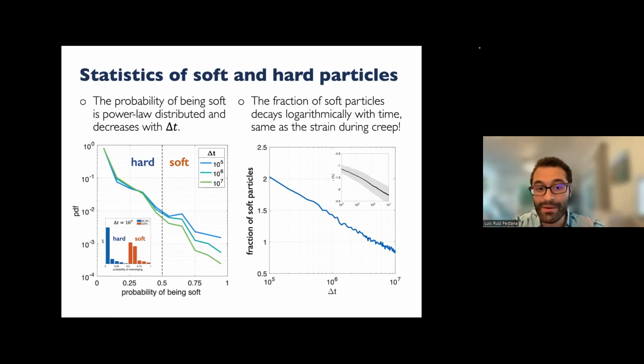This is very interesting because they start looking like defects, right? In crystalline solids, defects don't need to be very common or very frequent or very abundant in terms of the overall bulk material, but they do govern the response. And what we find is that these soft particles, at least, correlate perfectly. Again, I don't have causality here, but they seem to control the creep, or it's a hypothesis that they control the creep in glasses.